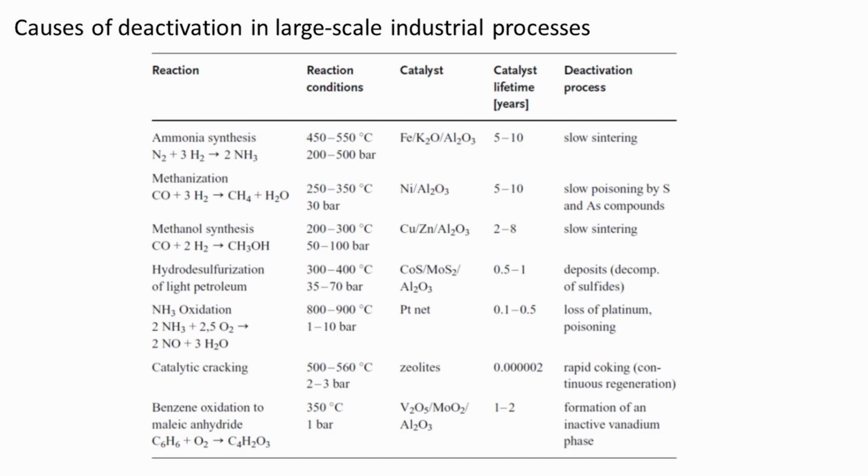Catalytic converters used to reduce emissions from gasoline or diesel engines may be poisoned or fouled by fuel or lubricant additives and/or engine corrosion products. If the catalytic reaction is conducted at high temperature, thermal degradation may occur in the form of active phase crystallite growth, collapse of the carrier pore structure, and solid-solid reaction of the active phase with the carrier or promoters.